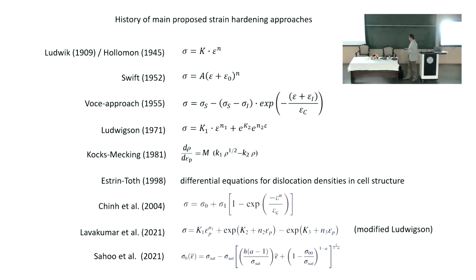It has a story. This strain hardening function, an analytical empirical function for macroscopic fitting, comes from crystal plasticity. I have been using a certain crystal plasticity strain hardening approach in my polycrystal modeling for more than 30 years. I was thinking whether in a similar form we can integrate it, because that's a rate equation used in polycrystal simulation with incremental calculation, so if we can integrate and simplify it to get something macroscopic.